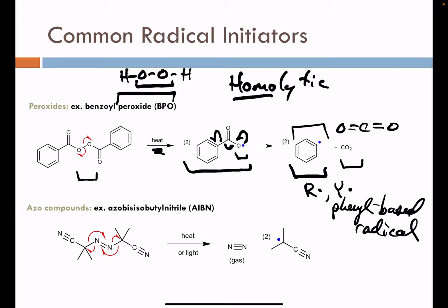We would see this phenyl group at the leading head of the polymer. Another famous one is AIBN. This can be triggered for degradation using heat or light. So photopolymerization, photopatterning can be enabled here. And here, the reaction is driven in part by the elimination of gas, as well as the reactivity of this azo functionality in the middle here.